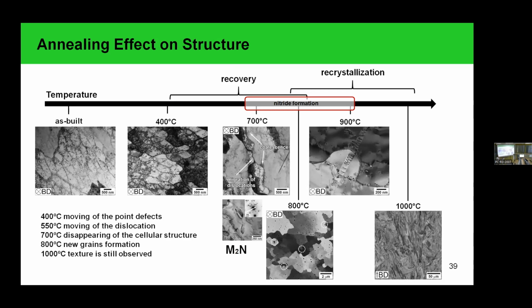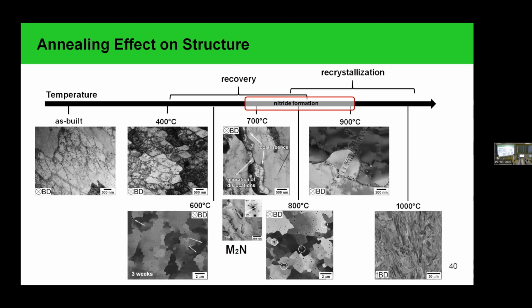Also, in the range of 700 to 800 degrees Celsius, using transmission electron microscopy, we observed small precipitates of this phase. At 900 degrees Celsius, we see precipitates of nitrides, which is associated with the presence of nitrogen in the initial powder which we used for our printing process. But even after long heat treatment, like 3 weeks, we see the formation of these new phases on the grain boundaries, even after annealing at 600 degrees Celsius. But interestingly, we see the stability of the cell structure at this temperature.